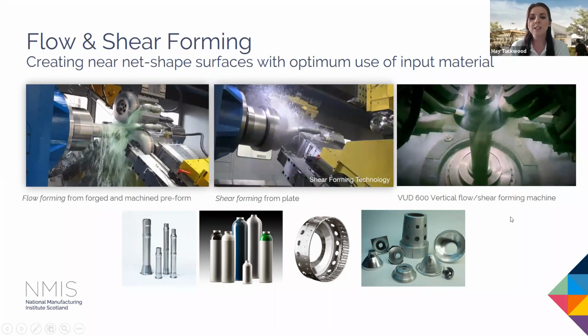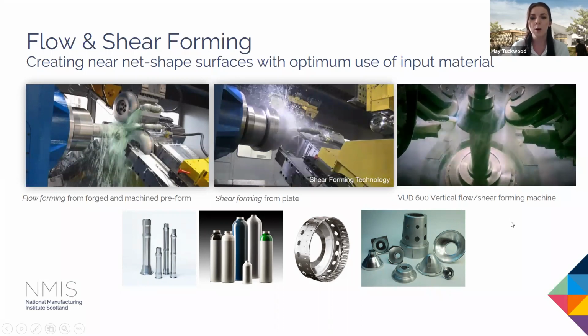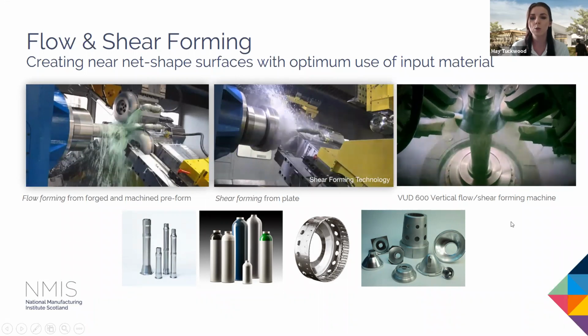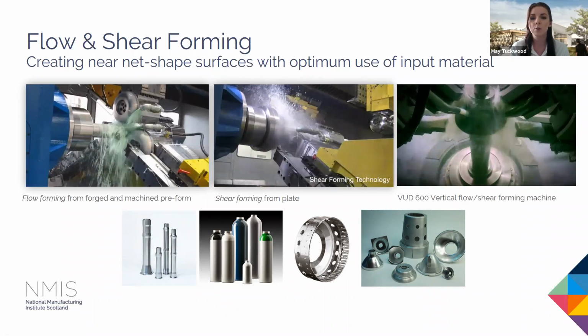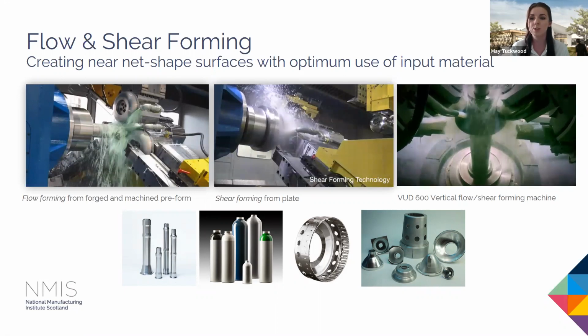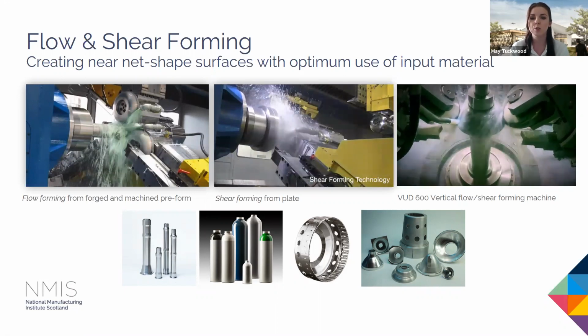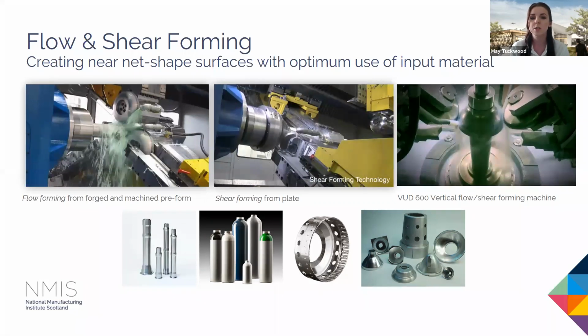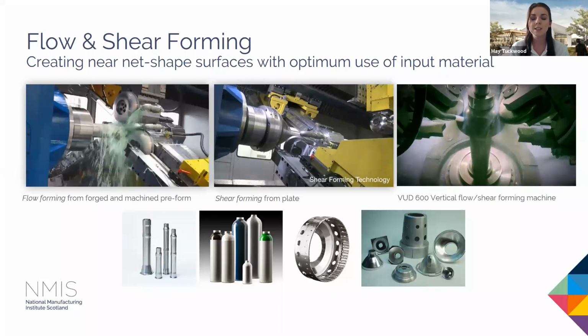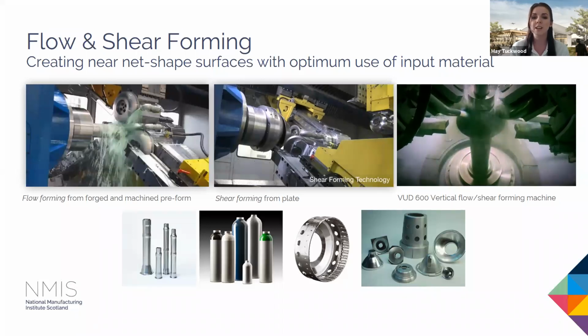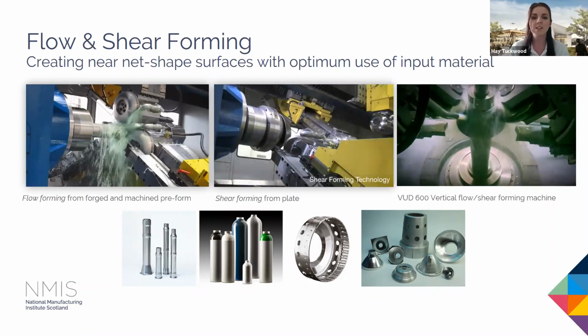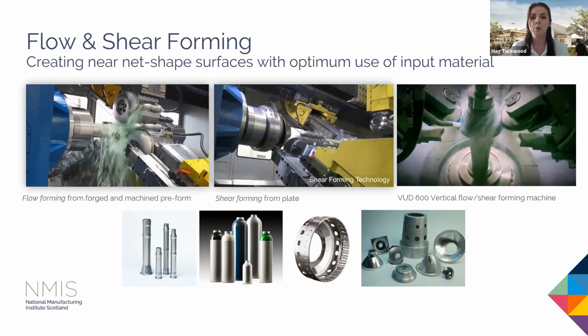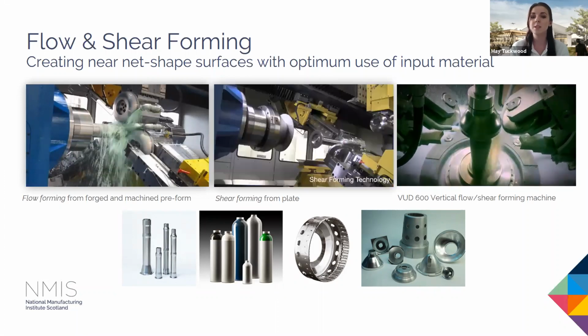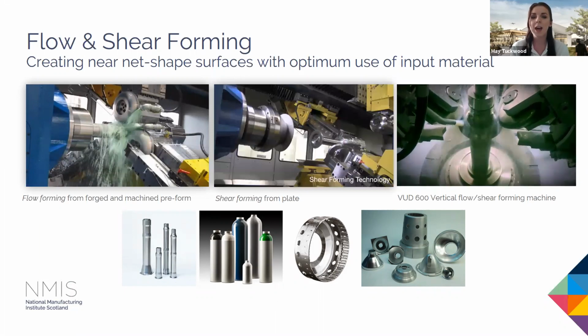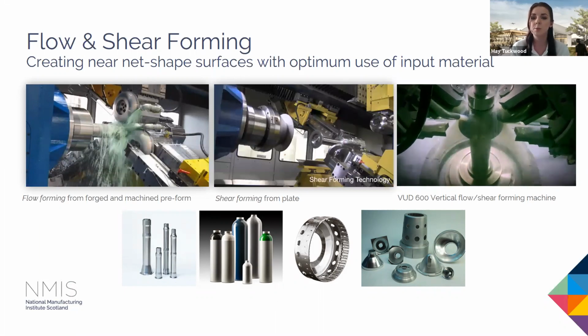Now on the left here, you can see an example of our vertical machine. So this particular bit of equipment, we very often refer to this as our small flow former. Now it's small in footprint, however, it can do larger diameter range as compared to the horizontal machine, up to 800 millimeters. Now its vertical setup gives us much more flexibility. So we've got things like angled roller housings, which means we can form a contact point with the material at different angles, but we can also add things like features onto the parts.